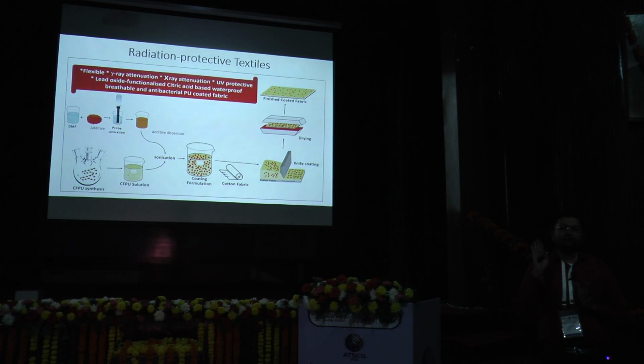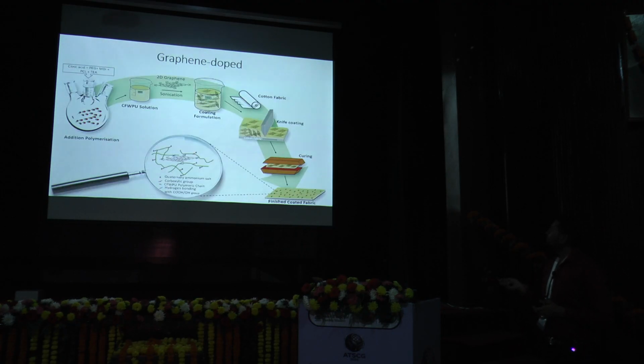So a single layer of this fabric can reduce gamma ray radiation by some percentage, which is much more than the reported products in the literature. And the product is generally multi-layer. So we don't use only a single layer of thin cotton fabric. So you can have multiple layers of these cotton fabrics, and then you have very efficient gamma ray reduction. So that is also achieved out of this.